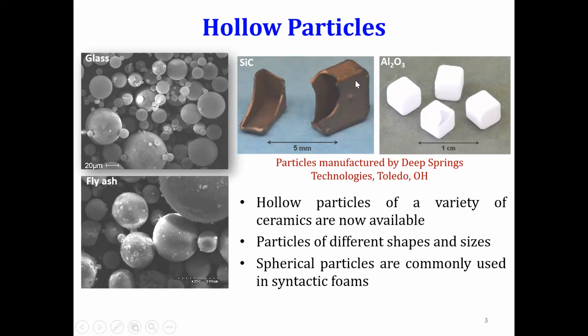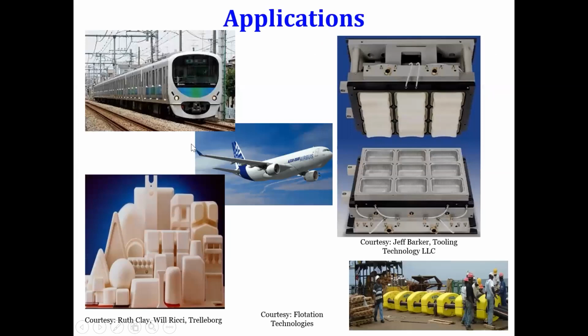We prefer spherical over cuboids because cuboids have corners, whereas hollow spheres don't have corners and no stress concentration effect. In addition to that, because of the spherical particles compared to cubes or cuboids, the resin spread is always better. And more or less all the manufacturing methods from conventional to advanced can handle these spheres with equal ease. There are various applications, and the applications are still evolving and pushing the limits, from presently railways, aerospace, thermoforming plugs, which are made up of foams, and then most commonly used buoyancy modules in marine systems are made up of these foams.